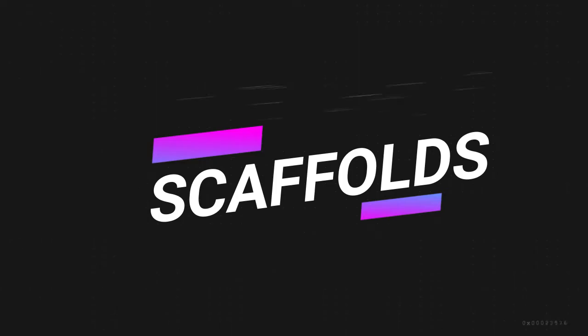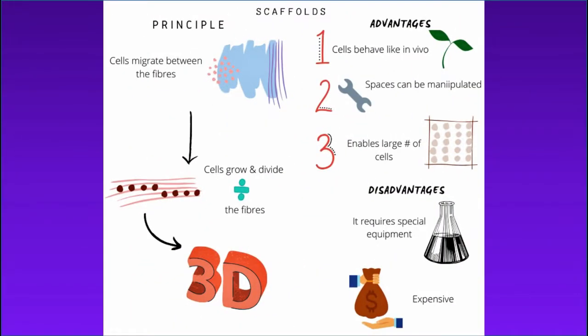Prefabricated scaffolds can alternatively be used for 3D culture. Cells seeded into such scaffolds can migrate between fibers of the scaffolds and attach to them. The interstitial space between fibers is filled by cells as they grow and divide, forming 3D cellular structures. Collagen, laminin, alginate, and other biodegradable materials are commonly used for this purpose. These products can be processed to form hydrogels for use as 3D cell culture scaffolds.